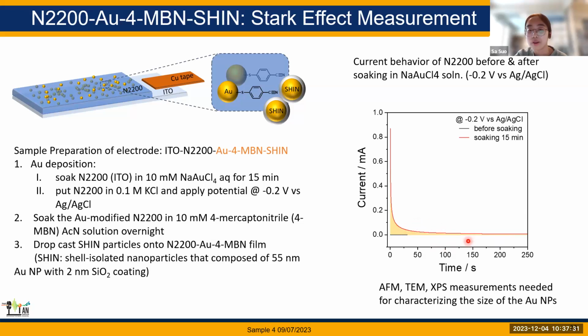However, we also really need to capture how large the gold nanoparticles are. I think AFM, TEM, or XPS measurement on this gold deposited electrode will be really helpful for characterizing the size of the gold nanoparticles. But my personal guess is that the size should be really small, because this gold size cannot give us the proper resonance for our Raman spectra. So I think it is pretty small.